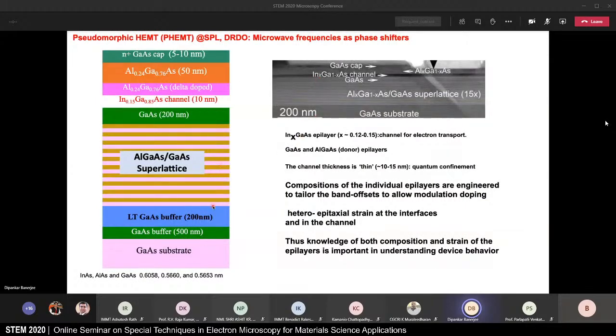And you can see that it ranges from a few nanometers in these active layers to something like 50 nanometers or even 500 nanometers. And what we have to do in understanding the material science of such devices is to understand the composition of the individual layers, because they are engineered to allow band offsets, which allow modulation doping. We have to understand the heteroepitaxial strain of these interfaces in these channels, because they affect device performance, and therefore the knowledge of both composition and strain in these epilayers are very important in the understanding of this device technology.